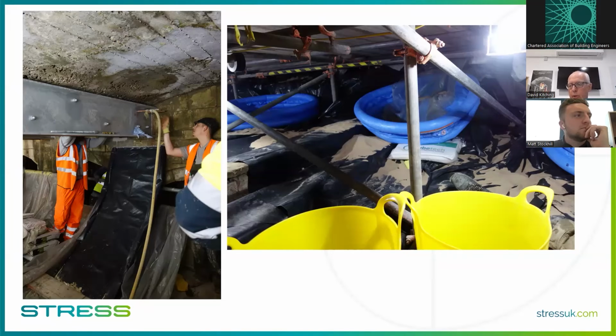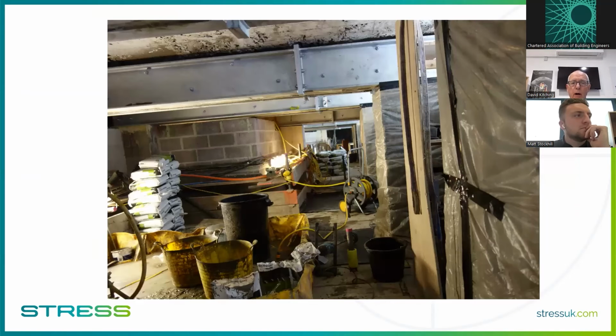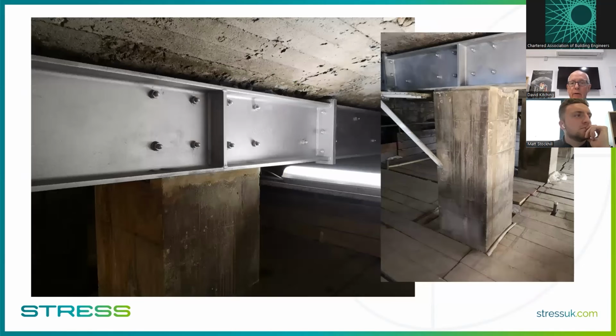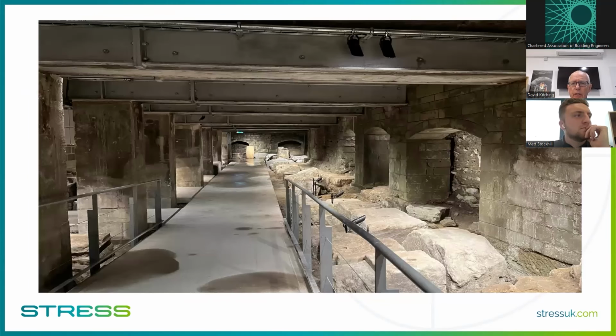Archaeologists were obviously paranoid about spilling grout onto the Roman pavement, so we used kids' paddling pools, buckets, and polythene, and all sorts of pieces. And it went very well. We put in a huge volume of grouting, but it worked an absolute treat, and there it is finished. And it is actually now a new part of the museum, so you can go down there and look at the archaeological remains, and actually do a bit of digging, do a little bit of archaeology yourself. So that's what you see.